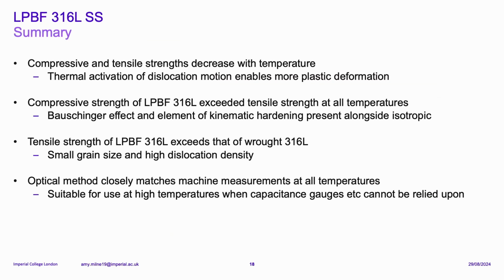So just in summary, the compressive and tensile strengths decrease with temperature as we expected, and the compressive strength of 316L exceeded its tensile strength at all temperatures, likely due to the kinematic hardening present alongside the isotropic element. The tensile strength of powder bed fusion 316L exceeded that of the wrought due to the small grain size and high dislocation density, and the optical method closely matched the machine measurements at all temperatures, which means it's suitable for use at high temperatures where other gauges can't be relied upon due to their limitations.